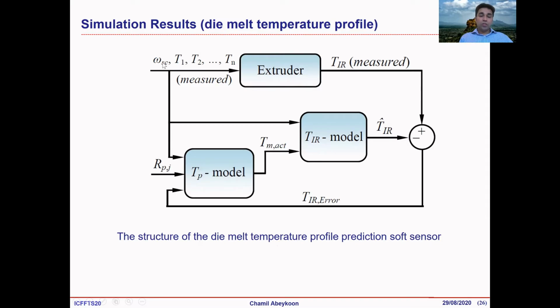Screw speed, set temperatures, and then here in the extruder we just use an infrared sensor to make actual measurements as well at the end of the die. Okay, so now we just use our TP model to predict the melt temperature profile. Once we have a melt temperature profile across the die melt flow, we can get the average melt temperature profile. So we just feed that into the TIR model.